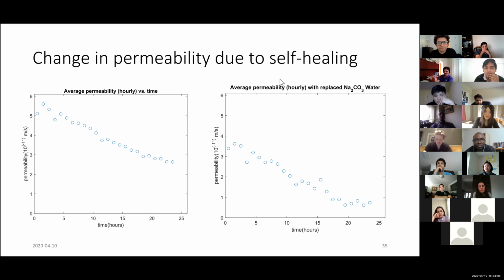Are there parallel plots here that you have for an increased pressure or increased stress in the cylinder? I do have them. It's just that once I unload everything and reload the sample again, usually in this one I got a similar permeability. Usually I get a different permeability the next time I load it. So I can analyze those as well, but we can't really compare one graph to the other graph. We can only compare through the graph, like what is happening. Do you have the data beyond 20 hours?